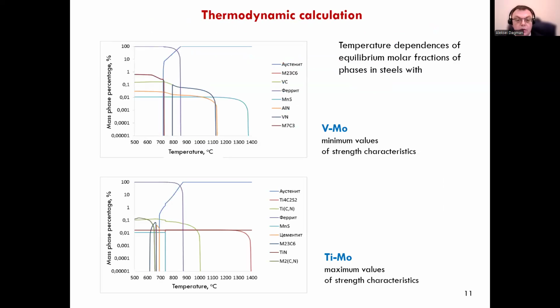This slide shows the results of a thermodynamic calculation performed for vanadium-molybdenum and titanium-molybdenum microalloying system steels with minimum and maximum strength values, respectively. It can be seen that the total content, mass percentage, of the phases VC and TiCN are approximately the same. However, due to the kinetic features of the separation process, which depends on the presence of molybdenum in the steel, vanadium carbide is released with a significantly low molybdenum content, approximately 0.20 weight percent, and the particles are larger and their number is smaller.